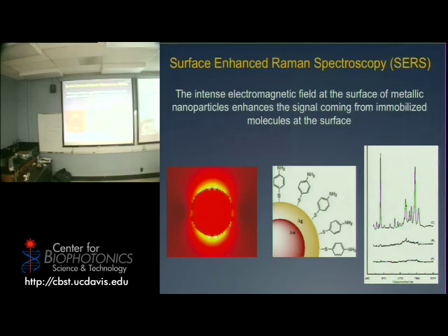And because of the intense electromagnetic field, they sense it, and there is this effect that can happen in a particular type of spectroscopy called Raman, but also fluorescence. We're not going to go into the details. So all you need to know is that at the surface, because of the electromagnetic field, funky things happen, and one of the things is that a molecule that ordinarily you will not be able to see much, you can actually see because there's an enhancement of the property you're trying to see. One is fluorescence and one is Raman. So here will be the signal of the molecule by itself, but when it's close to the surface of the particle, you can recognize some of the spikes become more intense, because the electromagnetic field of the plasmon couples with the property of the molecule.